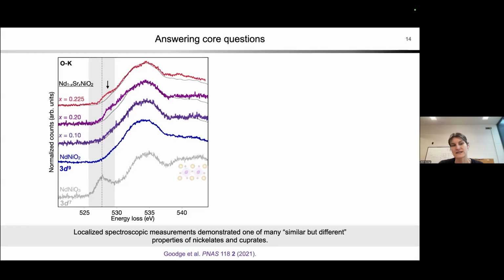And so this is actually how you tune superconductivity in these materials. What we wanted to know is what's really going on electronically as we go through these different superconducting phases. And what you see is this very subtle shoulder that starts to emerge under where I've marked with the black arrow. This was actually the feature that we went out looking for.